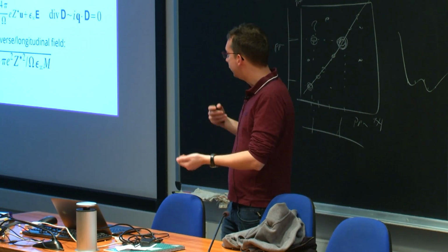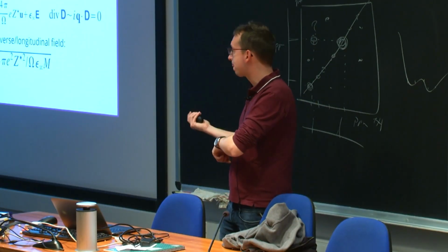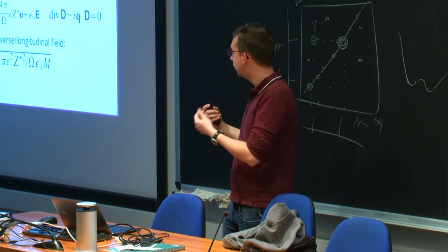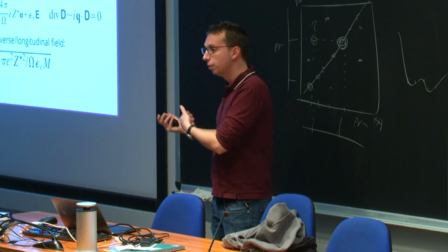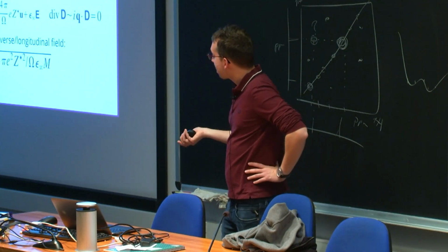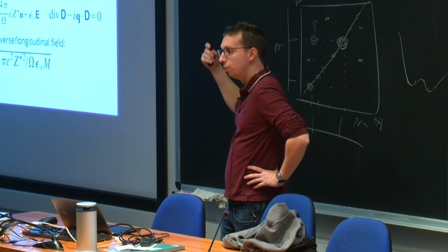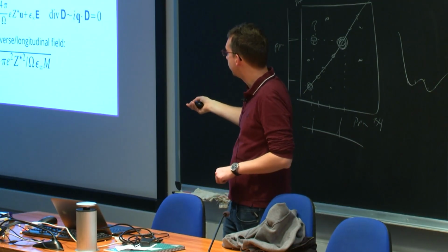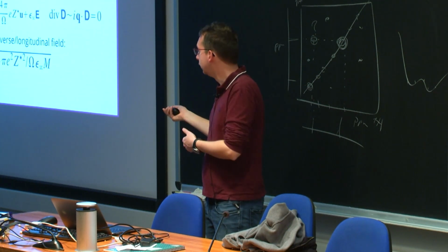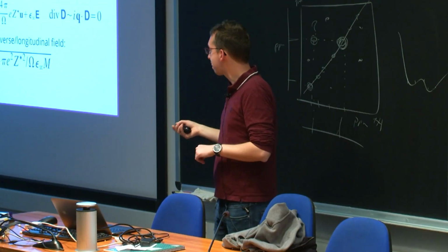And so it is interesting when you compare to experiment to try and see with and without effective charges, and so to understand how much the eventual screening caused by doping is going to influence the phonons. But okay, experimentalists are very aware of this problem. They know that you're going to put the LO-TO splitting because of effective charges. But sometimes you don't see the longitudinal mode at the different energy because it's screened by doping.